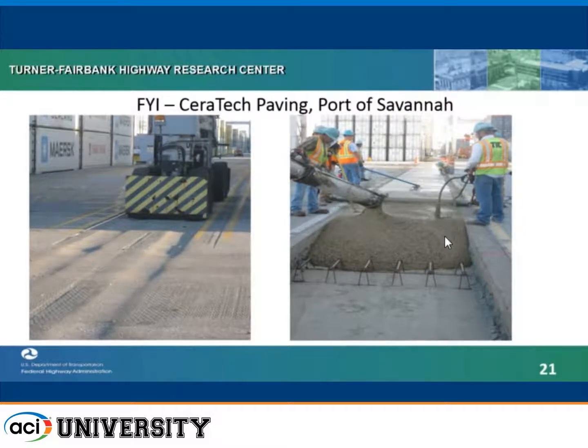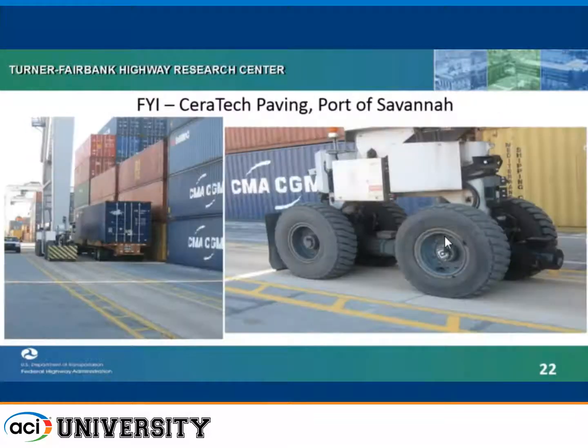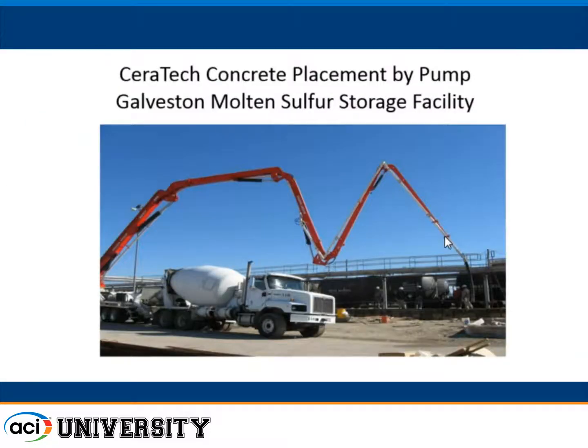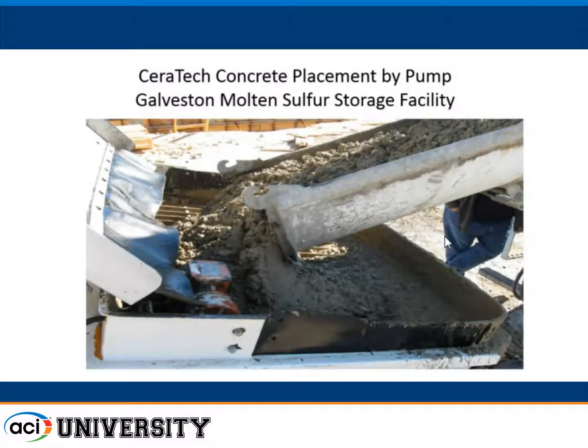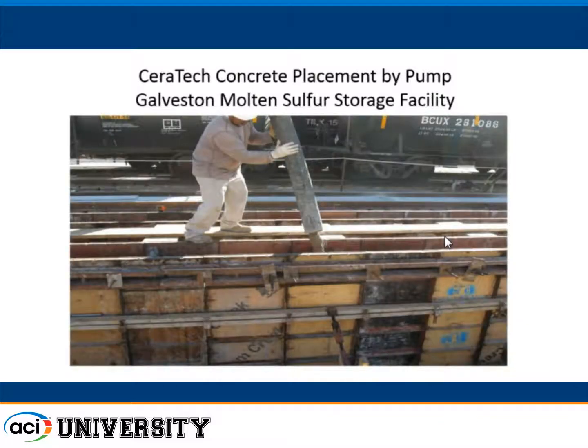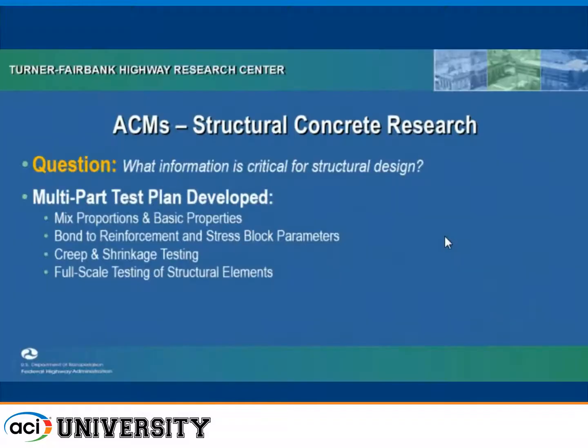CeraTech has been used in various industrial and transportation applications. This is just an example at the Port of Savannah. I went down and observed a project where they were doing paving. They were replacing the rutted asphalt pavement for these heavy cranes used to move the containers around in the port. And this shows the concrete actually in use in that particular case. I also observed a placement by pump with the CeraTech material, the 100% fly ash-based cement, in Galveston at a molten sulfur facility. In general, the concrete looked a little bit different maybe, but it went through the pump and was placed in a reinforced concrete wall with no apparent problems.